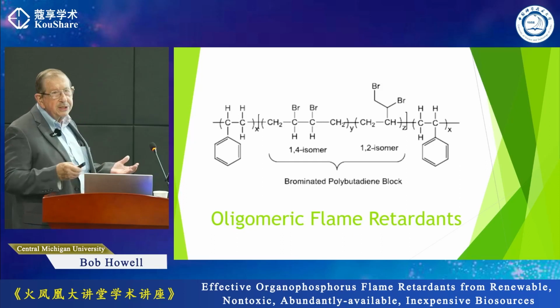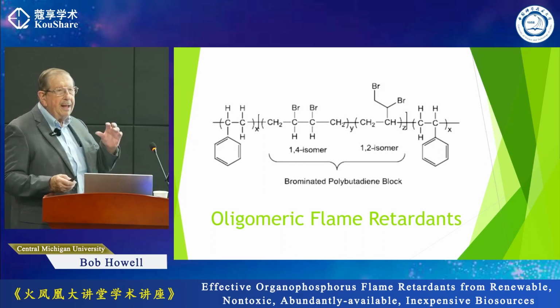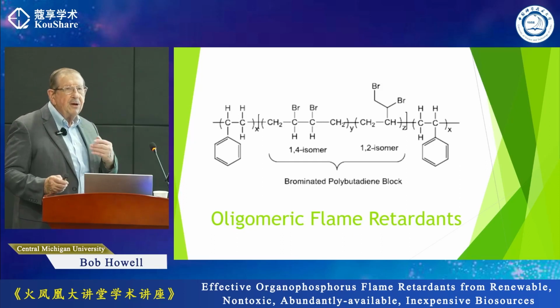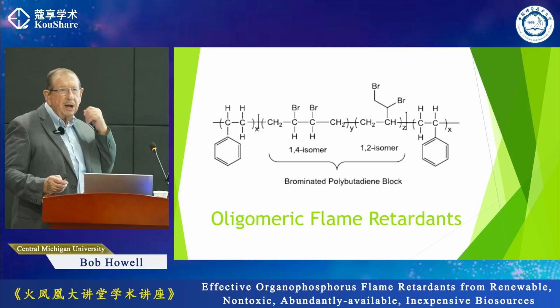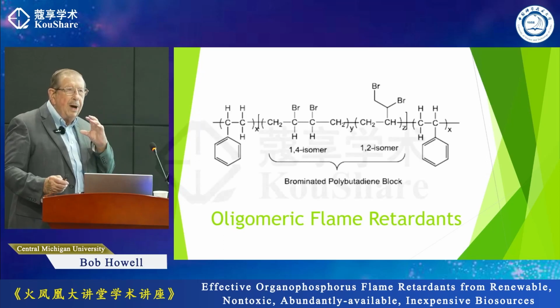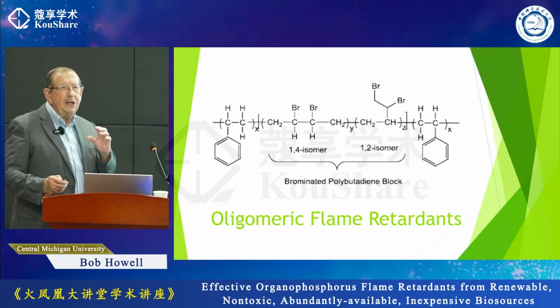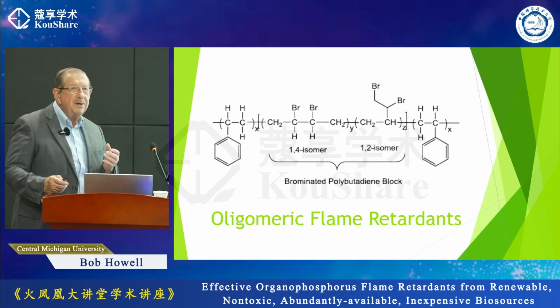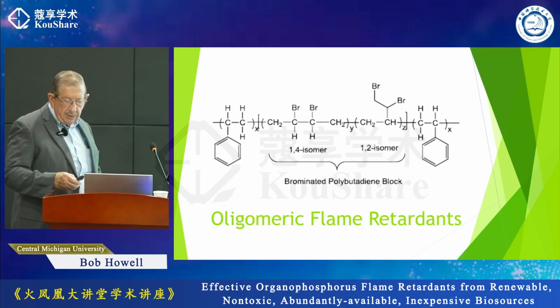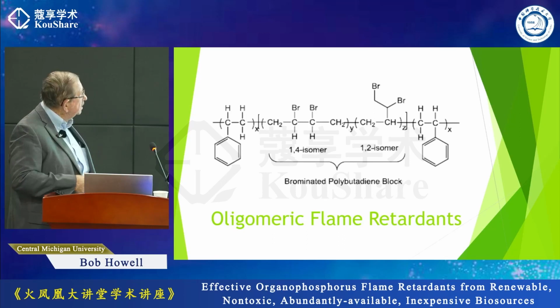So one approach to dealing with the leaching problem, the migration problem, is to use oligomeric materials. One has to be careful that the molecular weight is not sufficiently great that compatibility with the matrix is lost. So that's a concern in using these kinds of materials.